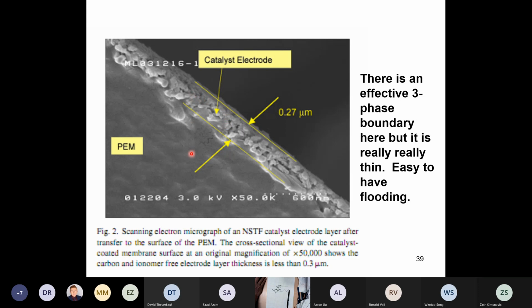You'd have your Nafion and then your catalyst on polyimide. You'd put a piece of paper top and bottom so that it wouldn't stick to the laminating rollers, and you just run it through. And this is what you would get. So this they called a catalyst-coated membrane. And everybody at 3M had all their jargons. You know, they had GDLs for gas diffusion layers, MEA for membrane electrode assemblies, and then they had CCM. CCM was a catalyst-coated membrane. So you're seeing a CCM here. And the catalyst layer turns out to be very thin, and the Nafion gets sort of pushed into it. So that means you get good contact of protons to the catalyst.